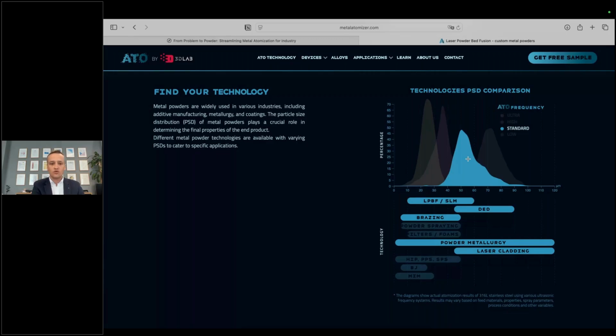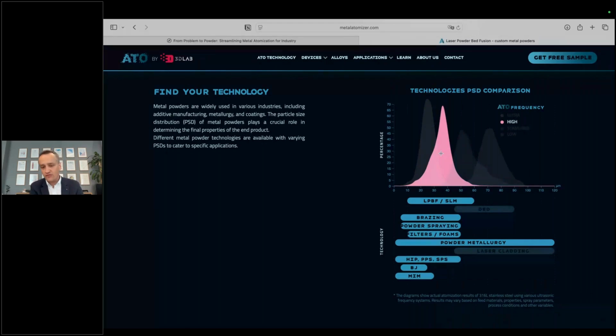But for those customers who are asking us for smaller particles, we can switch to a smaller particle size distribution by implementing a higher frequency system, like for example, 52 kilohertz. Another group of our customers is asking us for even smaller particles. That's why a few months ago during the TCT Rapid show in Detroit, we presented the ultra high frequency system, the 72 kilohertz system, which allows you to switch to even smaller particles with the biggest amount of powder between 20 to 25 microns.